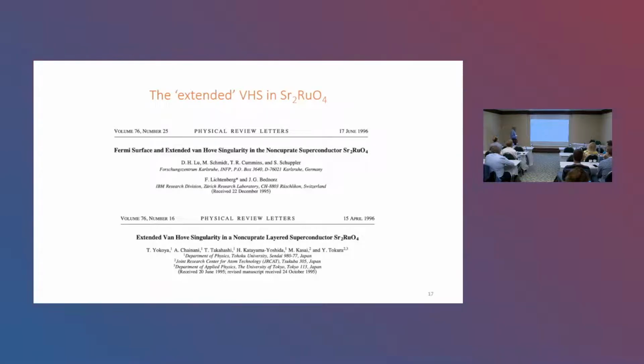Second, extended Van Hove singularity in strontium ruthenate 214. This is a different strontium ruthenate. It's a bit more famous because of the superconducting properties. It was the first non-cuprate layered superconductor observed. And in 1996, you see a paper by one of the co-authors, Bednorz, who talk about Fermi surface and extended Van Hove singularity in this non-cuprate superconductor. And at exactly the same time, extended Van Hove singularity in a non-cuprate layered superconductor by a different group. Good. We thought that the notion of extended there is a bit vague. Now we have the tools to analyze this.